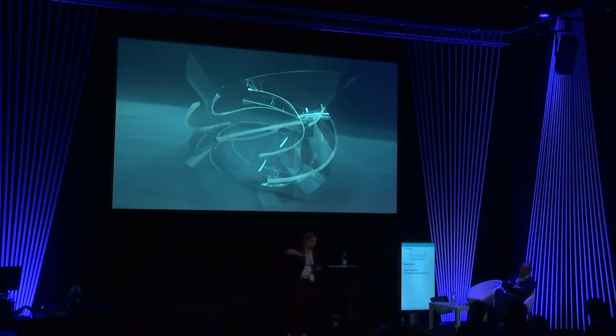So the first lesson was the bonding method or bonding material that I used, the clear VHB tape. I had chosen this over epoxy, for instance, for immediate bonding. That was very important. The epoxy I tested with, especially in the summer in New York City, had extremely long curing time, so that was not appropriate to my cold bend structure, which wants to flatten back again. So I needed to have immediate bonding, and it's also quite flexible. So throughout the stages of construction of the structure, I did need some rotation at the joint. That's why the VHB tape was really a good solution at the time.